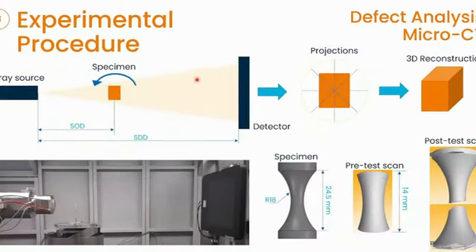The first step of the experimental procedure is a microcomputed tomography scan of the specimen. In the micro-CT, the machine takes projections of the specimen in various rotating positions, and then those projections are used for a 3D reconstruction of the specimen, so that the internal defects can be detected. The source object distance divided by the source detector distance is what gives the final resolution in the projections.